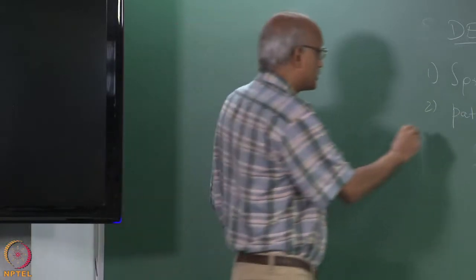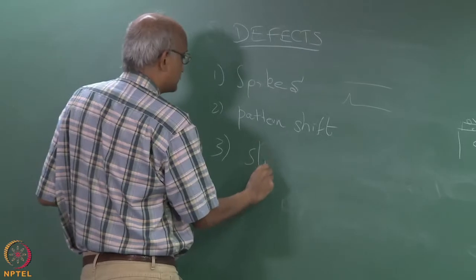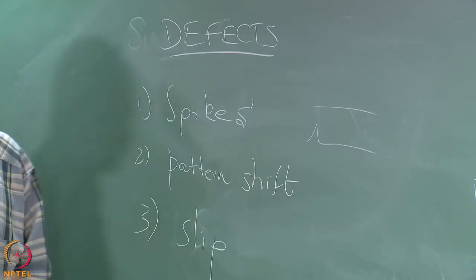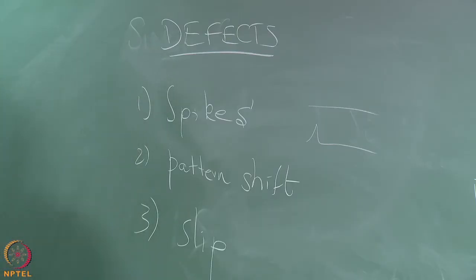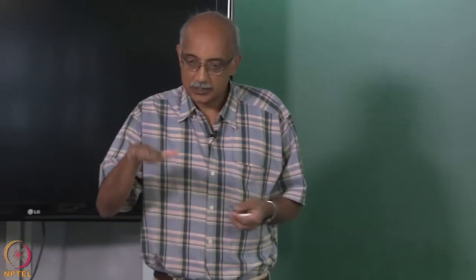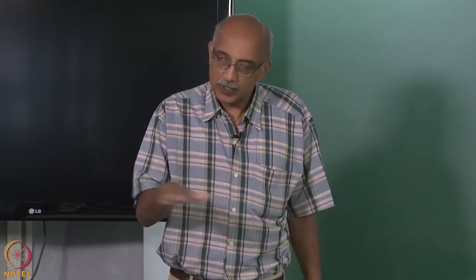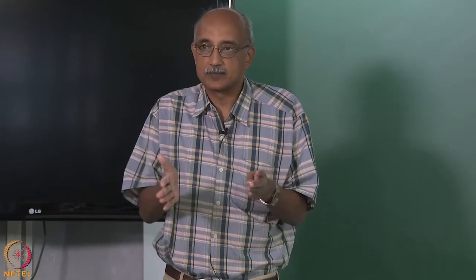Another type of defect that we see is slip. Slippage can occur between successive layers of the film, because when the CVD process happens, you are essentially putting down the CVD film one layer at a time, one molecular layer at a time, that is a few angstroms at a time. You are assuming that when the second layer deposits on top of the first layer, it's going to just settle down and stay, right? But that may not always be the case.